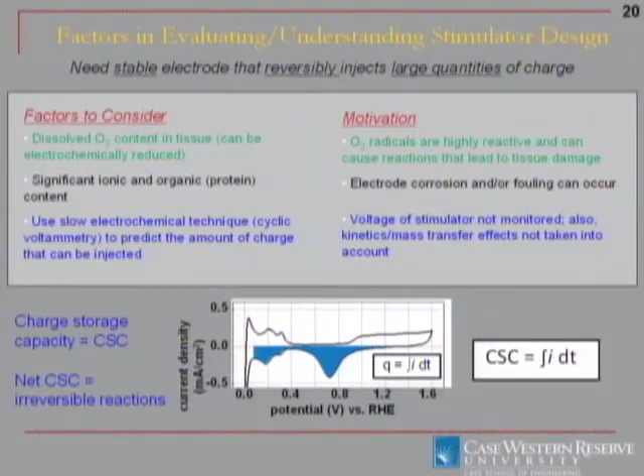There are several factors to consider because it's an electrochemical process. Dissolved oxygen is there, so I'm going to show you a little bit of data related to that. And of course, that could be important related to oxygen radicals. There is significant ionic and organic content in the tissue, which may result in fouling, may affect the actual performance of the electrode. And then just in general, because they're using this slow electrochemical technique for evaluating electrodes preliminarily, what happens when we compare that to the actual more relevant time scale, that fast pulsing situation. Okay.